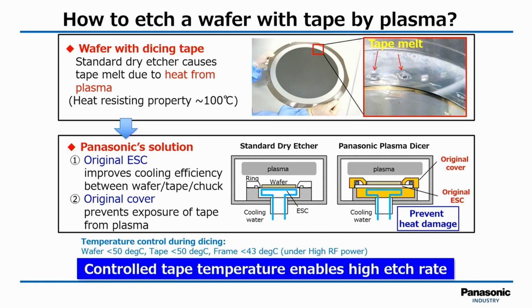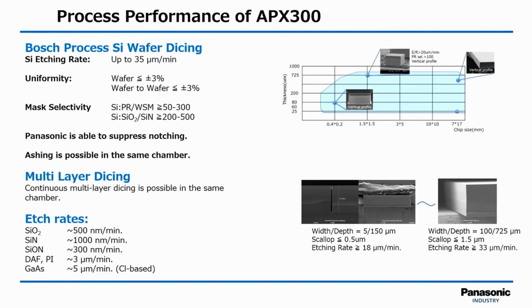And the cover ring, which is designed for the size of the wafer, which is lowered after the wafer is entered into the chamber to protect from the wafer edge all the way to the edge of the frame. So very important for us to maintain wafer temperature and tape temperature during dicing so that maximum etch rate can be achieved. So wafer remaining less than 50 degrees Celsius, tape remaining less than 50 degrees Celsius, and frame less than 43 degrees Celsius through our own independent experiment.